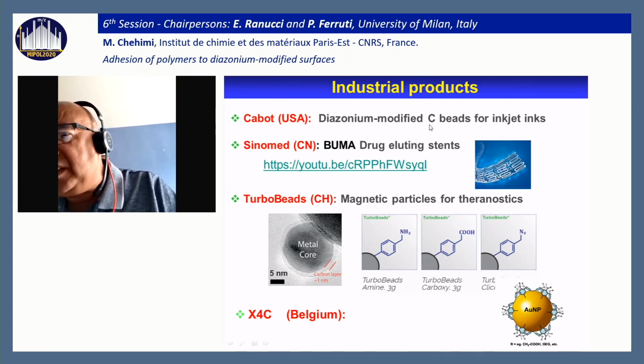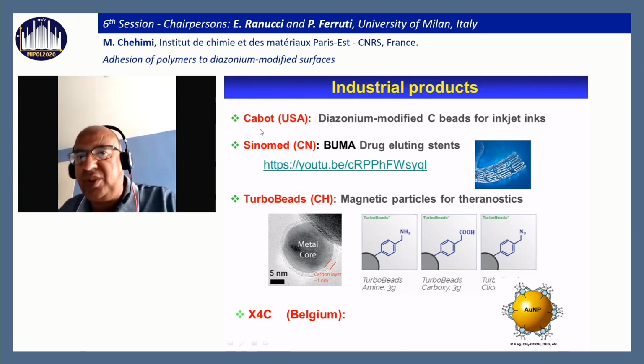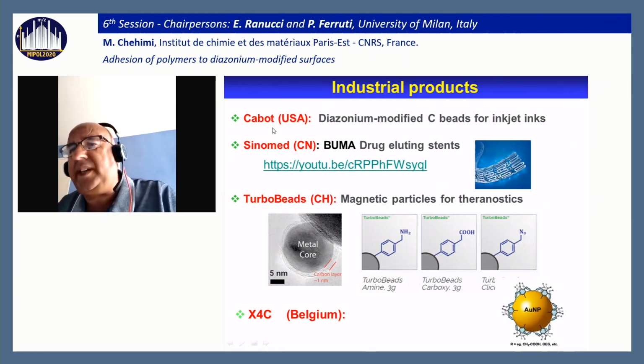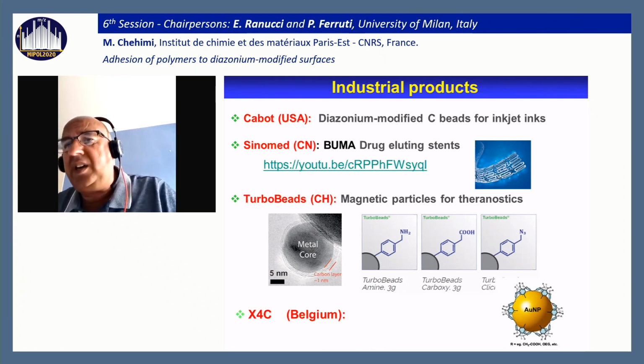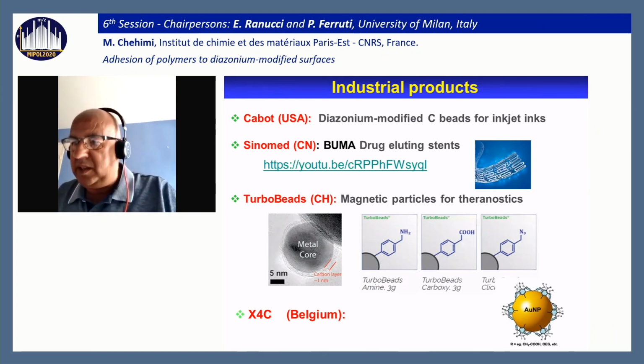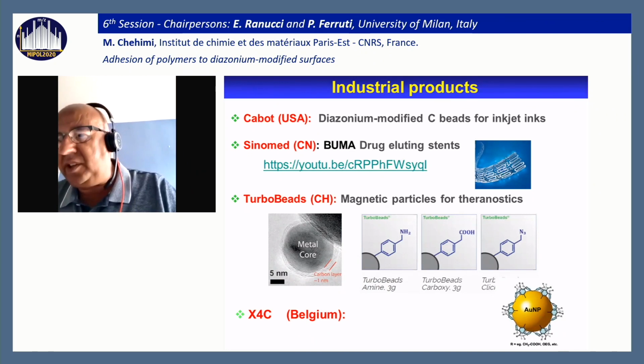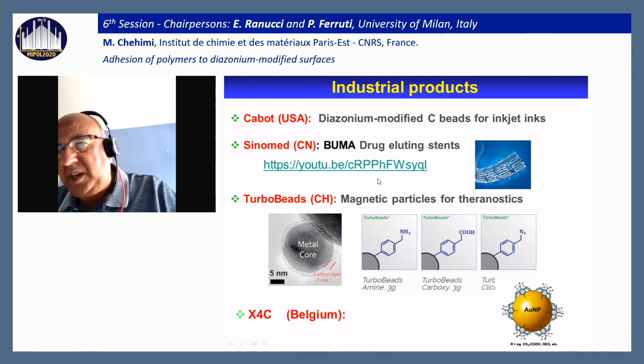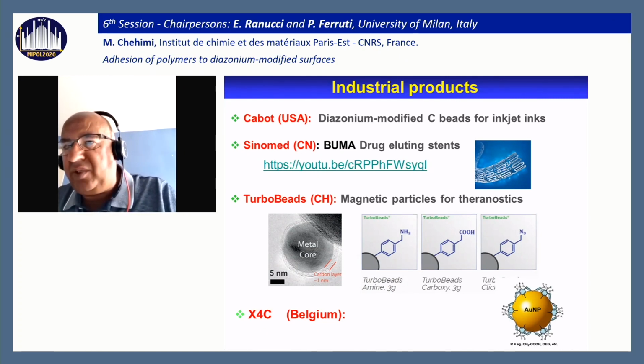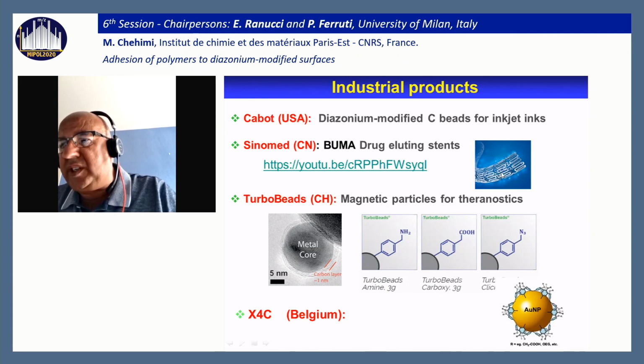the diazonium-modified carbon beads for inkjet inks produced by Cabot a long time ago in the United States. And actually Cabot has collaborated with Chris Matyjaszewski to prepare carbon-polymer nanocomposites, using the diazonium salt as a compound to provide a surface initiator for ATRP. Sinomed has exploited the patent by Christophe Bureau and Jean Pinson, and now they produce stents modified with diazonium salts as a coating for drug-eluting stents.